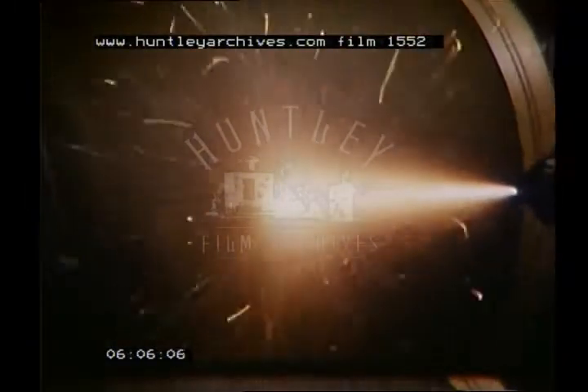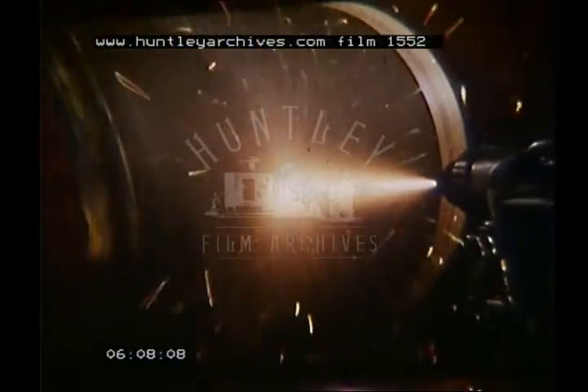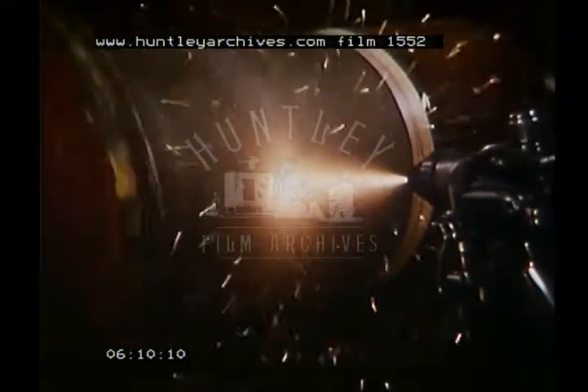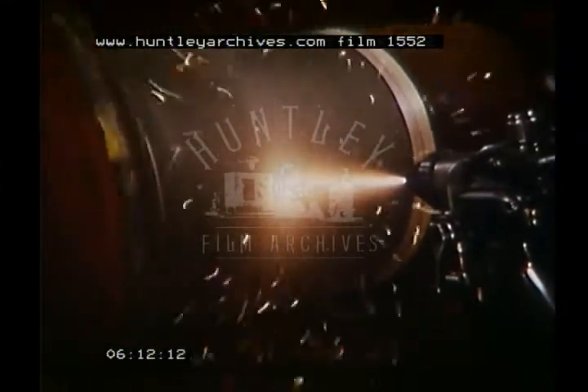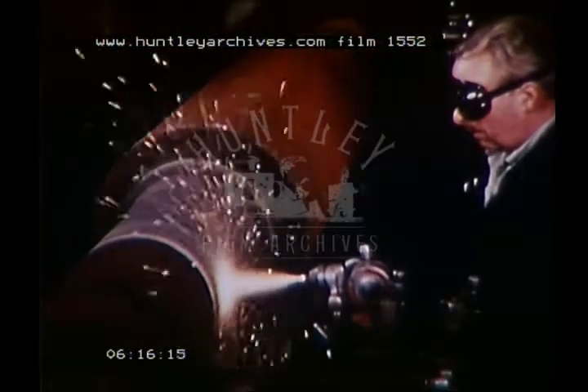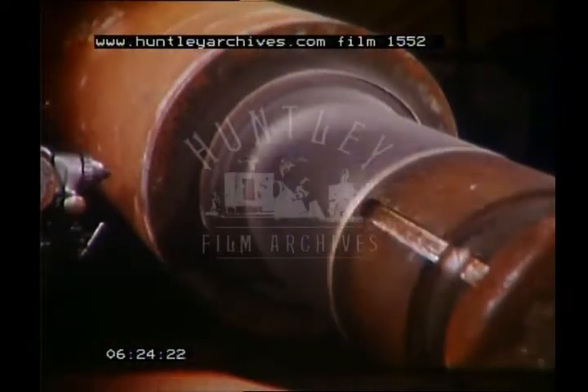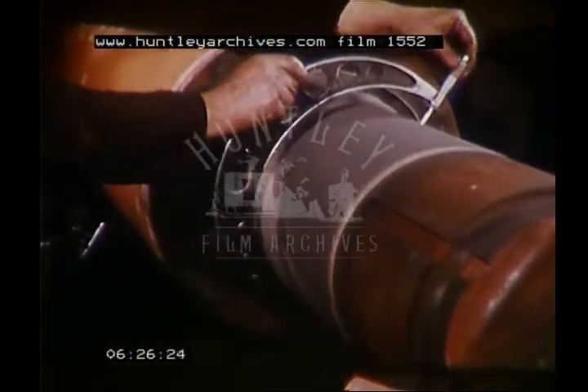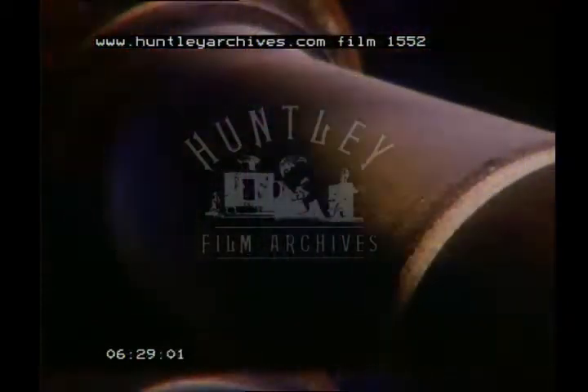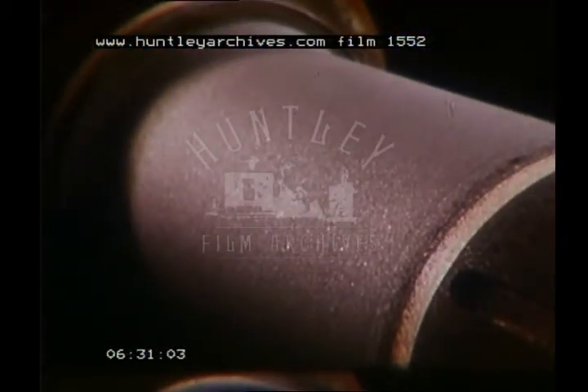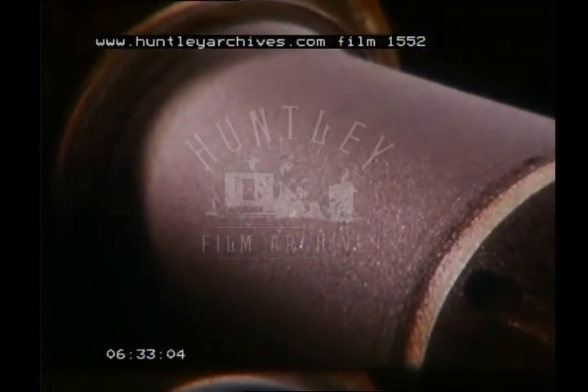After extensive periods of use, most work rolls can be successfully re-hardened for further service, but reheating and requenching inevitably produce distortion. The main problem is to correct the portion of the roll to which the bearings are fitted. If this portion has to be repaired, it has become common practice to use metal spraying. The majority of rolls treated in this way have given entirely satisfactory service, but this type of reclaimed roll should be handled more carefully than an untreated one.